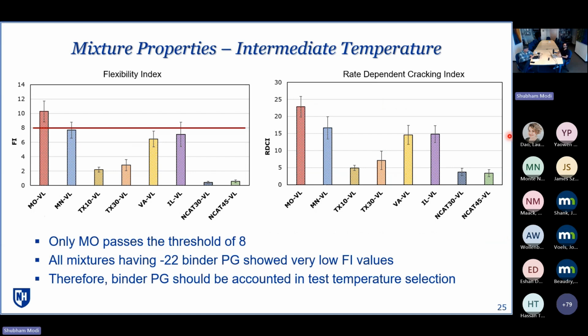And on the mixture results side, at intermediate temperature, we can see that only the Missouri mix is passing the threshold of 8, whereas all mixtures having minus 22 PG showed very low FI values, as shown by these arrows. The Missouri one was having the minus 34 binder in it, whereas these three mixtures had the minus 28 binder grade, whereas all these lower values had minus 22.